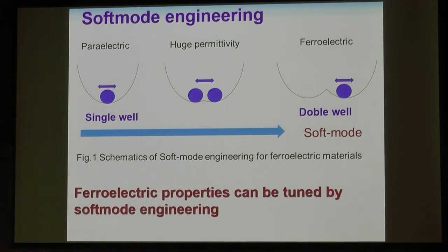As shown here, on the potential surface, if we have a single well, this is a paraelectric. Then the ion moves very little around this position. And if we make it soft mode, we have a double well here. It becomes a paraelectric to ferroelectric phase transition. Then the ion moves into this small well. And between these two phases, we have a very huge permittivity, as shown here.